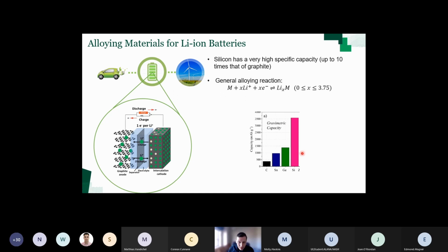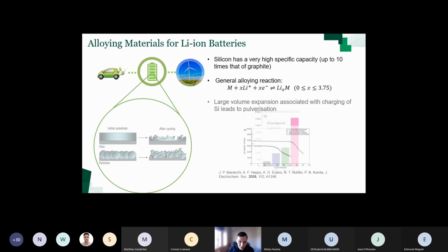So that results in the gravimetric capacity of silicon being an order of magnitude higher than it is for carbon. So you might ask, well, then why don't you just swap the anode material for silicon? And of course, it's not as straightforward as that, because along with this alloying reaction you get a very large volume expansion. If you use a microscale electrode or a film of silicon, basically it just pulverizes. The large volume expansion, which can be upwards of 300%, just causes the material to pulverize. If it pulverizes, it loses contact with the current collector, and after very few cycles you'll see the capacity begin to just fall off a cliff.